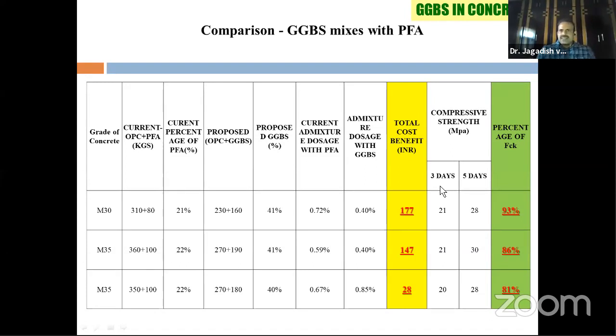When you compare with fly ash, because each of the supplementary cementitious materials has its advantage, just to compare with fly ash for some of the mixes like M30, 35, for fly ash based mixes, you can see in place of 310 plus 80, wherein you have used fly ash, one can go for an increase in cementitious material. Like instead of 80, one can go up to 160 GGBS in place of fly ash, wherein the early strength requirement is a point, okay, wherein you can see the compressive strength you obtain. Similarly, for M35, in place of 100 kg fly ash, one can go up to 190 kg. So you can obviously get the advantage of both the strength and even the cost.